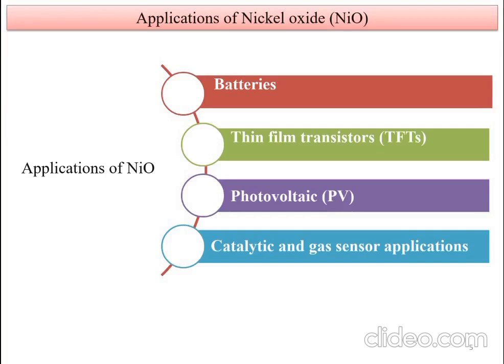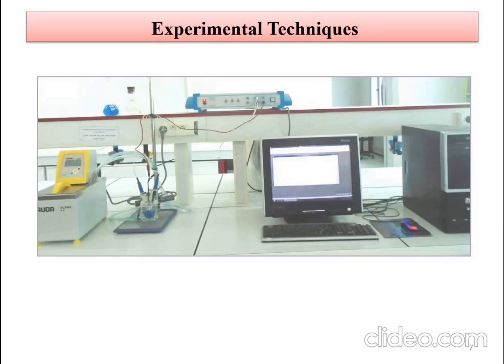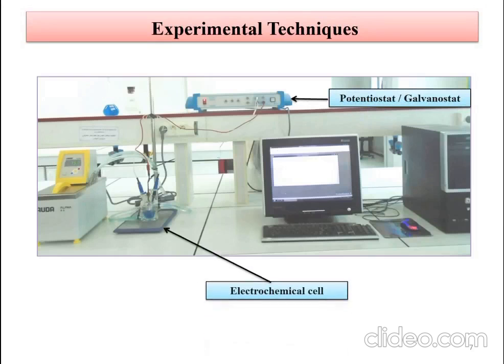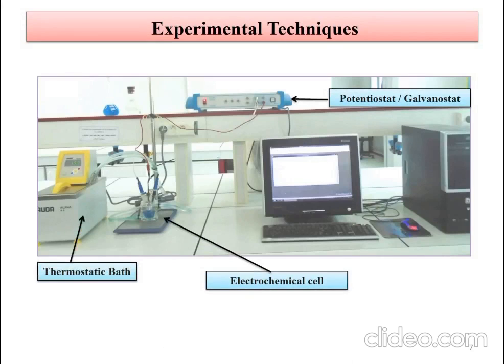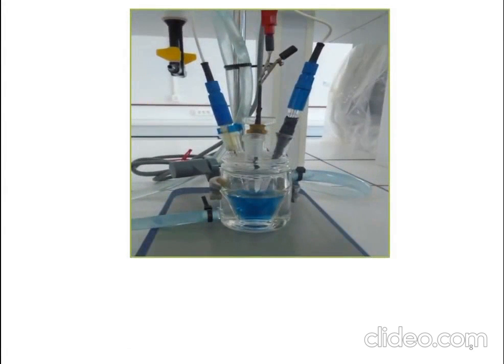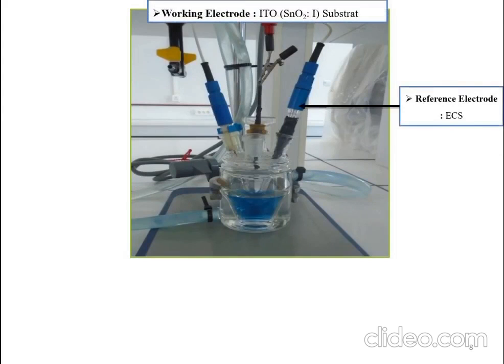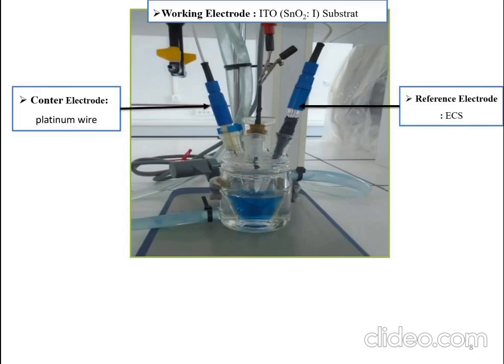Now we pass to the experimental techniques that we used. An electrochemical cell connected to a potentiostat and a thermostatic bath to control the temperature were used in the experimental procedures. Inside the electrochemical cell, we have three electrodes, which are a reference electrode of type ECS, and a working electrode. In the study, as we mentioned in the title, we used an ITO substrate. And finally, a platinum wire was used as a counter electrode. That's for the electrical part of the cell.